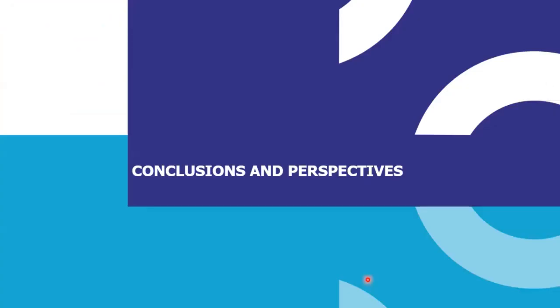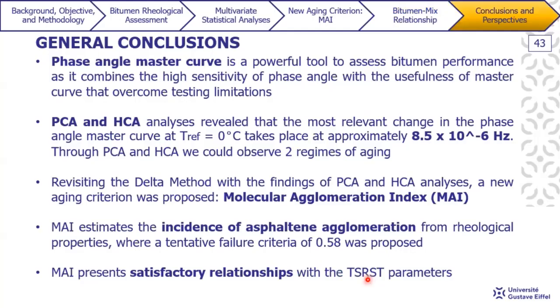So now I'm gonna present some conclusions and perspectives for further work. So phase angle master curve seems to be a powerful tool to assess bitumen performance as it combines the high sensitivity of phase angle and the usefulness of master curve to overcome testing limitations conditions. PCA and HCA reveal the most relevant changes that seem to take place in phase angle master curve at 0 degree reference temperature, which is approximately at 8.5 × 10⁻⁶ Hertz. And through this multivariate statistical analysis, we could also observe two regimes of aging.